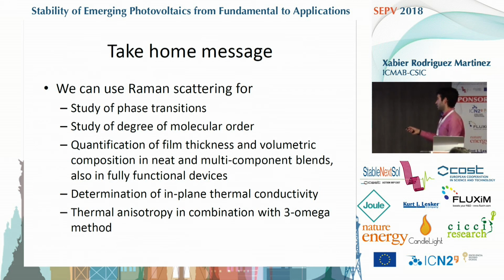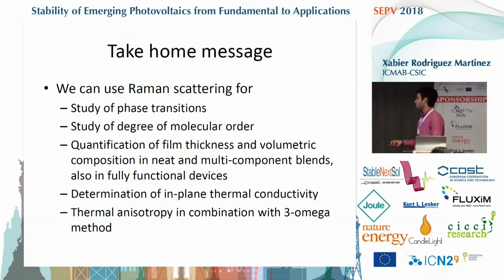Well, that's it. Basically, the take-home message is that you can use Raman scattering for several things: to study phase transitions, the degree of molecular order, quantify film thickness, composition in blends, and also to determine the in-plane thermal conductivity, which in combination with the 3 omega method allows you to look inside the thermal anisotropy in thin films.